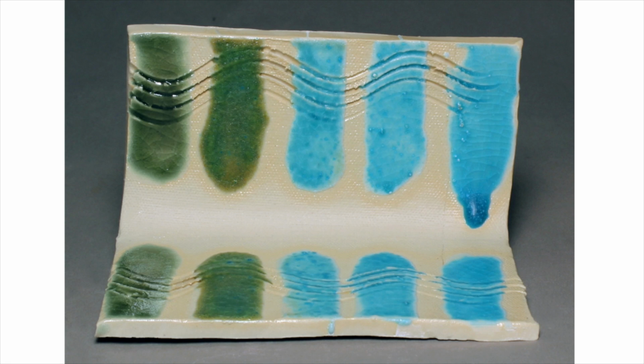Whereas, when the flux strontium carbonate is added to nepheline syenite and copper carbonate, it lowers the melting temperature of the feldspar and produces a matte surface quality with a turquoise color response.